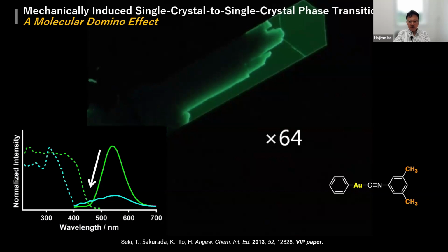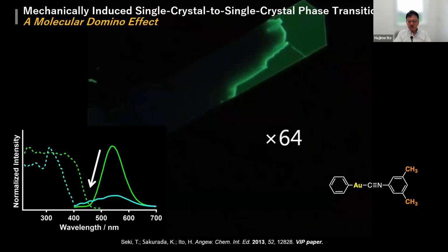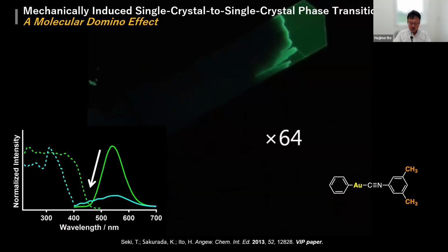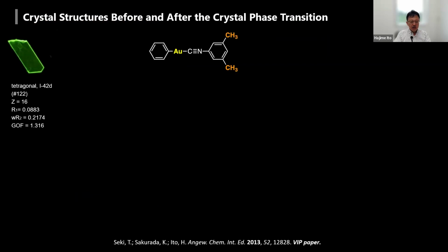Because the camera is not so good, you can see some blue color after the mechanical phase change. But this is a single-crystal-to-single-crystal color change, a single-crystal-to-single-crystal structure change.